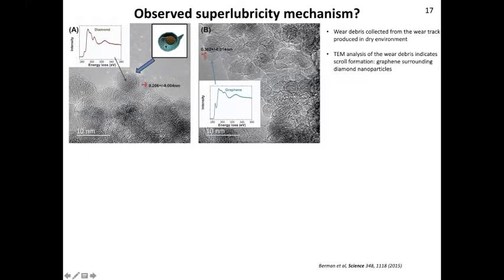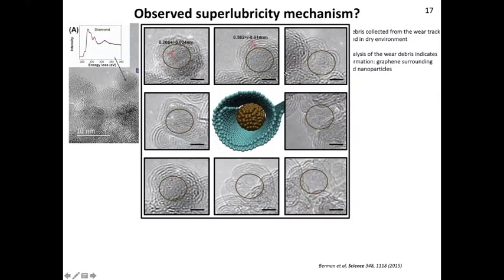So it actually showed that all our wear debris has some kind of structure similar to this one, where you have a diamond nanoparticle surrounded by a graphitic shell, kind of in the form of a carpet on our surface. And if we look closer by playing with the focus of our system, we've seen that this is happening pretty much everywhere. Even here, you initially see just the graphene flakes, but if you start to focus further, you see the diamond lattice inside the structures. This gave us the conclusion that probably these unique structures we found in our wear tracks, the diamond lattice surrounded by graphene, are the whole reason for observing the superlubricity.